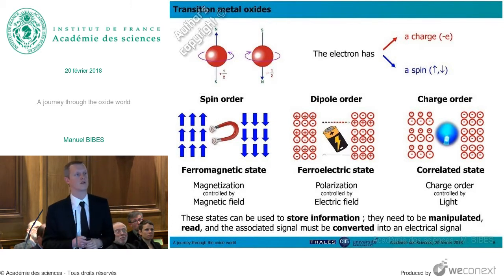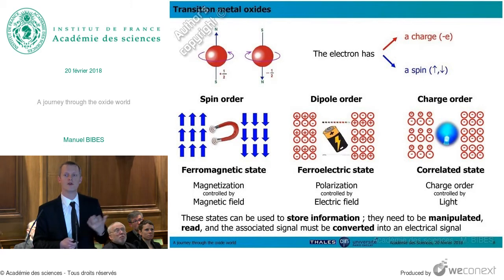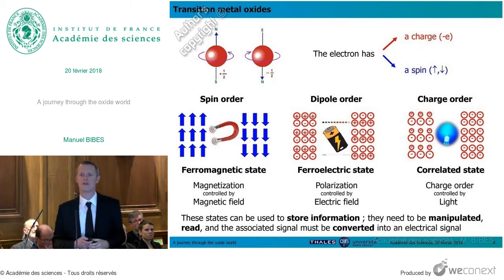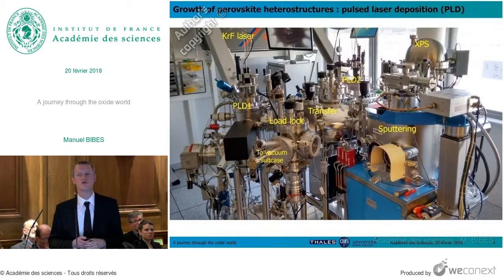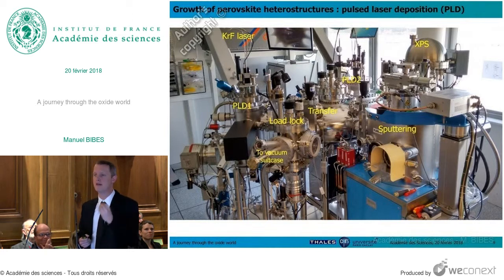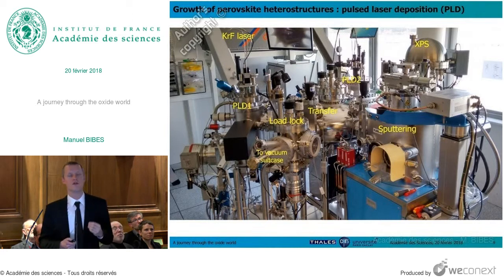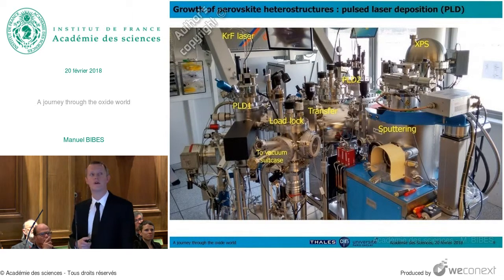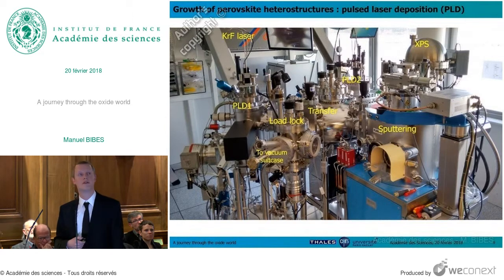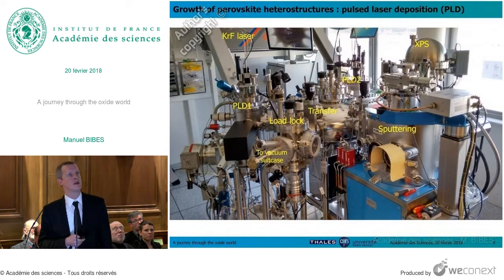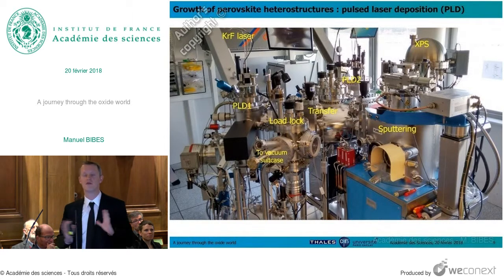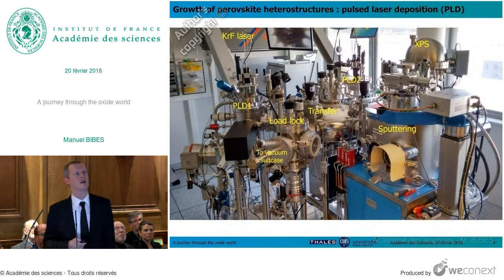So this is the kind of situation that we are trying to address and understand with our oxide materials. Before giving a few examples of these results, I want to show you briefly how we make these materials. We use a technique called pulsed laser deposition, PLD, and this is a picture of one of our growth systems in our lab in Palaiseau. All these chambers work in vacuum. We have pumps everywhere to have a very good vacuum.